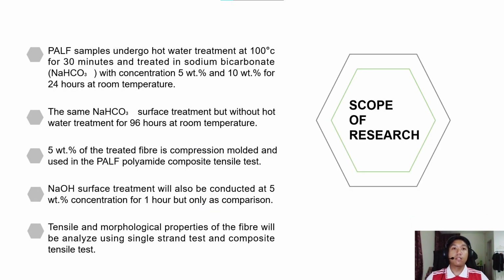This is the scope of my research. The fibers are soaked in a treatment of 5 weight percent and 10 weight percent of sodium bicarbonate. There are 4 different treatments. The differential between them is that for the 5 and 10 weight percent, we are adding hot water treatment for 30 minutes before they are soaked with the sodium bicarbonate. And we are also doing the alkaline treatment using NaOH as a comparison.